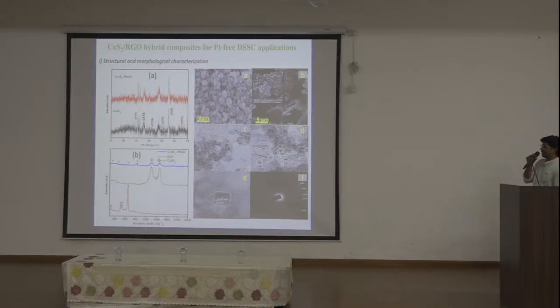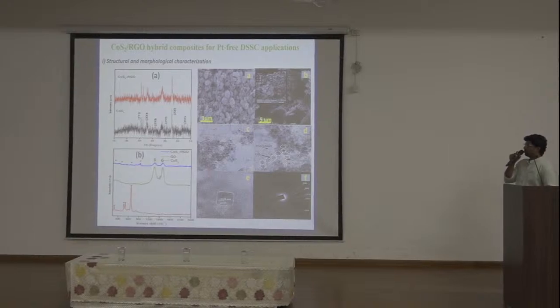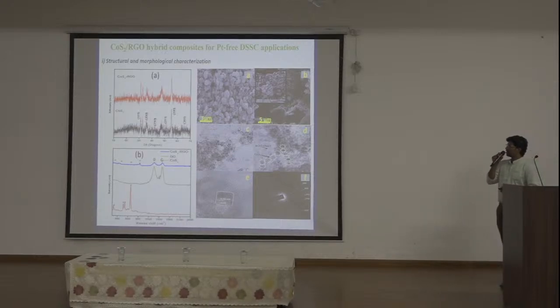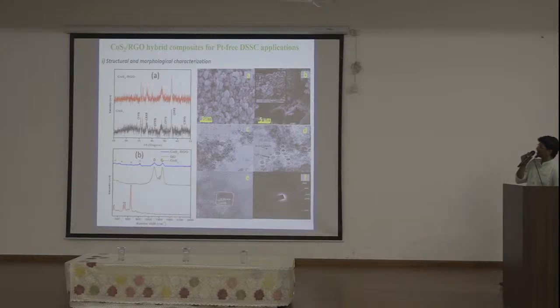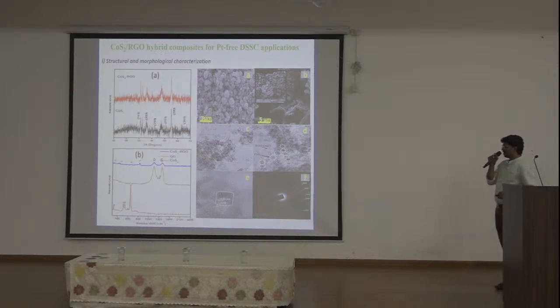I didn't mention the preparation technique here because of time; all the preparation uses the hydrothermal method. After inclusion of graphene oxide, it is entirely reduced. We didn't detect the characteristic peak of GO due to the copper sulfide and RGO interaction, which is very high.